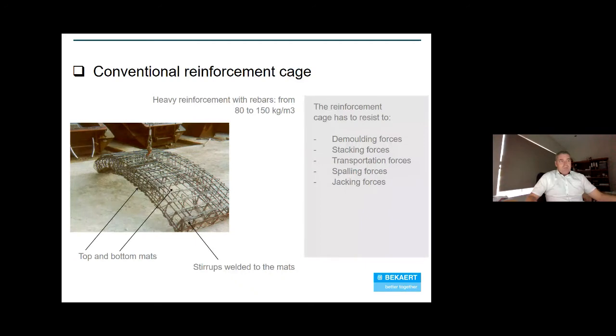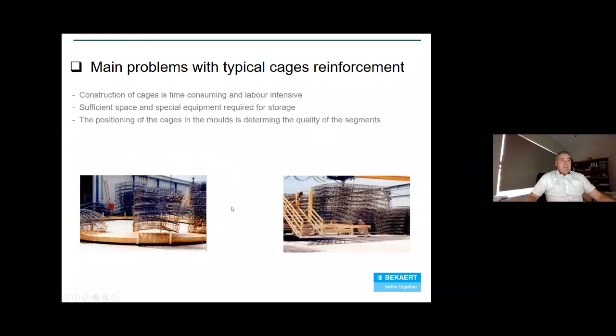I guess a lot of people have seen conventional rebar, heavy reinforcement, 80 to 150 kilos per cubic meter. Demolding forces, stacking forces, transportation, spalling forces, and jacking forces all are accommodated with this type of reinforcement. I guess the main problems of typical cages is the construction of the cage is very time consuming, very labour intensive. It takes a large amount of space for this operation to happen, and positioning of the cages in the mould is critical to get your quality of the segments.